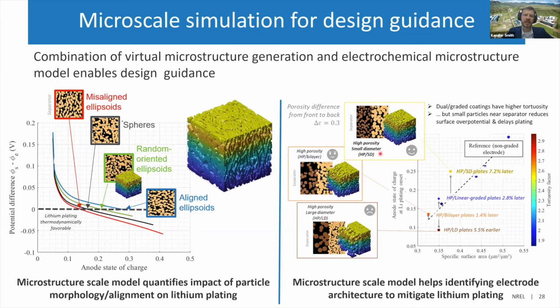And the best configuration that he's come up with, which Argonne National Lab is now building prototypes of, is a configuration where close to the current collector you have large particles and a low porosity, so very tightly packed particles there. And then the second layer, so you do a second coating layer after perhaps a first calendering step, with smaller particles, and you do this with a higher porosity. And so this type of electrode has a good balance of high surface area as well as a graded porosity. And you can actually have a similar surface area to if you had unimodal spheres and still get better performance from this type of electrode.